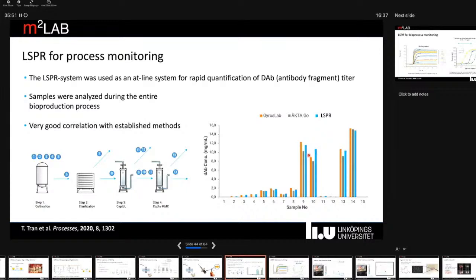we can outcompete essentially current techniques for at-line detection of, for example, titer, both with respect to sensitivity and dynamic range, but above all, the speed. I mean, here we can get a result within minutes on the product titer throughout the entire bioprocess, from the complex soup of biomolecules with very low titer concentrations in the upstream process, throughout the purification and clarification steps. And very good correlation to these other methods that typically take hours to get the same results.